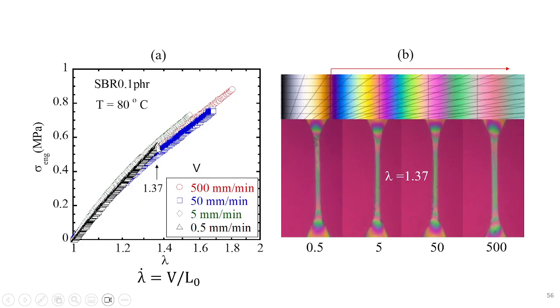And this is the actual result, that we use 4 different rates. If you look at stretching to 1.37 for the 4 rates, they all reach the same level of birefringence, indicating the molecular strain has all been reached instantaneously because it's a fast deformation.